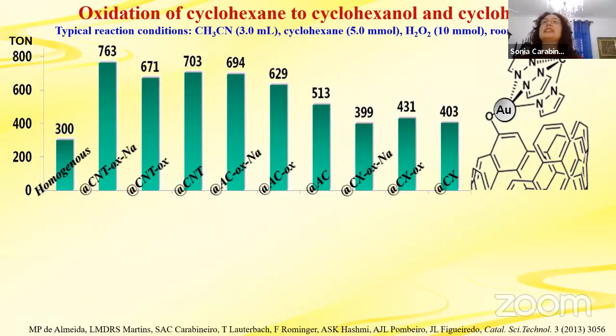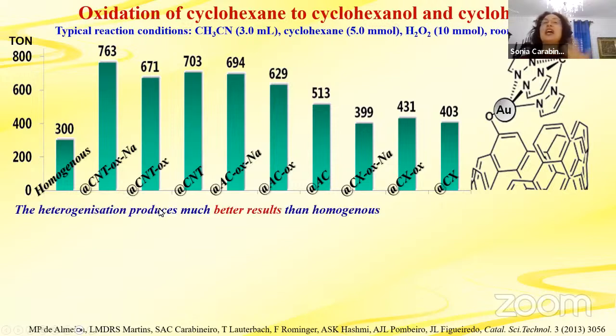So we have here the oxidation of cyclohexane. The best results were obtained with the anchorage of this complex, so those are the ones that I'm showing here. And here we have the homogeneous complex, so not anchored. So we have here this TON, the turnover number, which is moles of product per mole of gold. And we see that if we heterogenize the complex, we have much higher values. So heterogenization produces much better results than the homogeneous one.